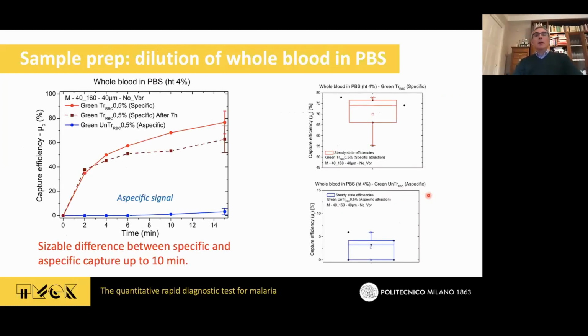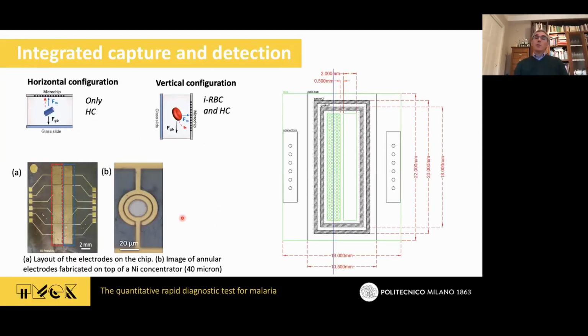And at the end of the day, we moved toward the real experiments, with the real sample preparation we are looking for, which is a very simple dilution of the whole blood in PBS. We take a blood sample, dilute 1 to 10 in PBS, and then check what is happening. In these experiments, we are measuring the capture efficiency as a function of time in the case of whole blood diluted in PBS, after spiking in some treated red blood cells in order to mimic a real malaria-infected blood sample. And what you observe is that you are really able, also in this case, which really represents the real situation, to capture with a good capture efficiency of around 80%. And there is a big difference between the sample with treated red blood cells and the sample without, at least up to 10 minutes. Okay, that's okay. We move towards the integrated capture and detection.